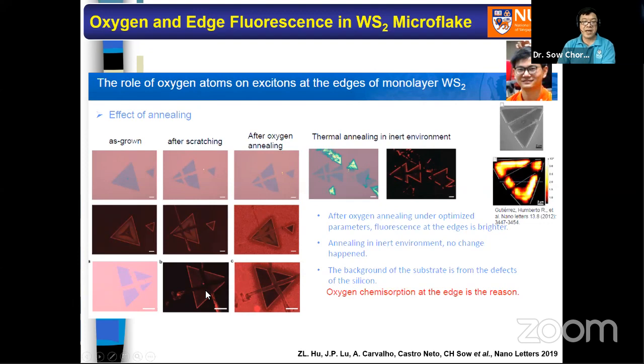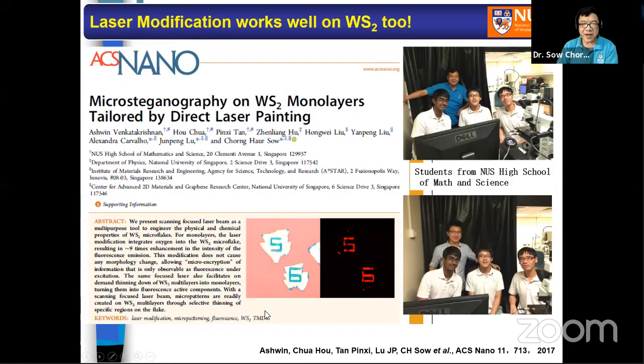And then he annealed this particular sample in an oxygen environment, and then look at this picture. Now the newly scratched edge, because of the annealing in oxygen, also gives bright fluorescence. So that gives us confidence that for the edge fluorescence, oxygen really plays a big role. Okay, and then we do a lot of detailed research. So the final two pieces of work I'm going to show you are something that is fun in our lab. Okay, this research uses a focused laser beam to do micro steganography in WS2 monolayer. Basically, you write a hidden message in the WS2.